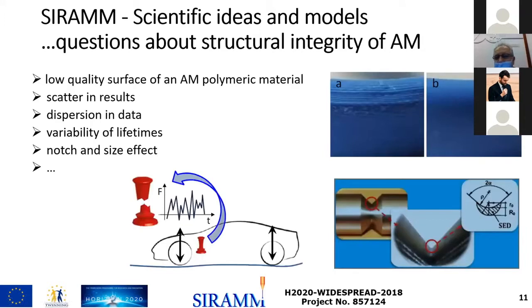So some drawbacks of these techniques: low surface quality of additive manufacturing, basically in polymeric materials, but also for metallic parts, quite high porosity, quite high scatter in results if you try to test them or to measure the dimensions of the obtained parts, dispersion of data, variability of lifetimes. In some cases, the durability or the fatigue strength of the components obtained by additive manufacturing is very low compared with other techniques, up to 10–20%.